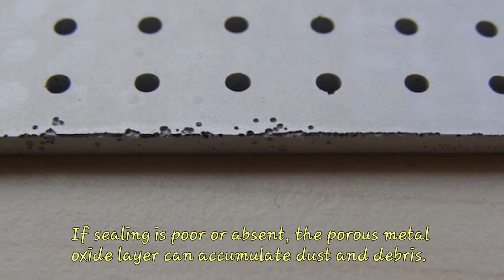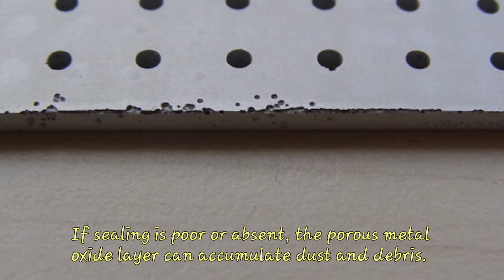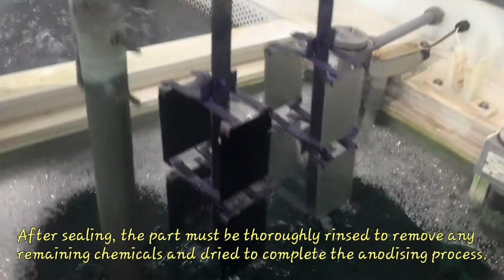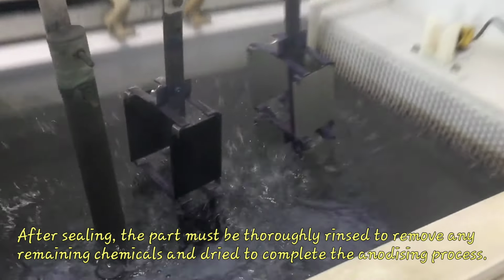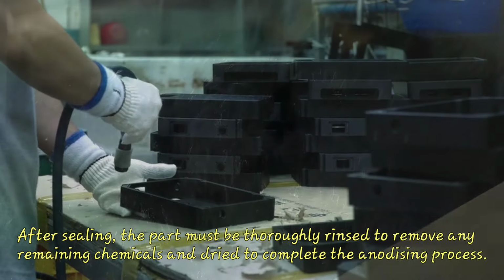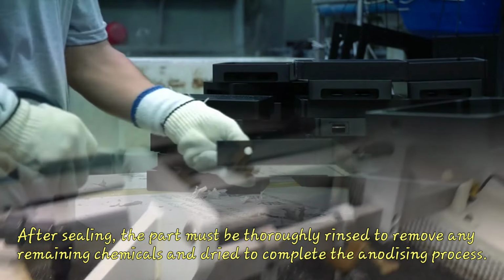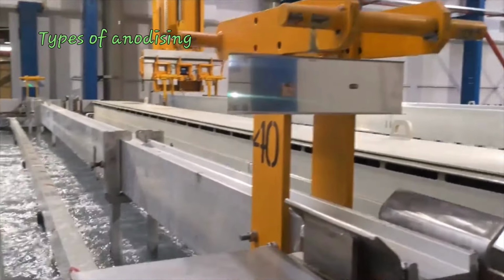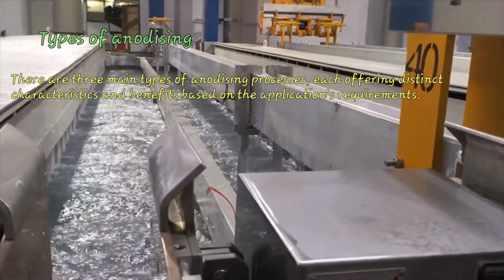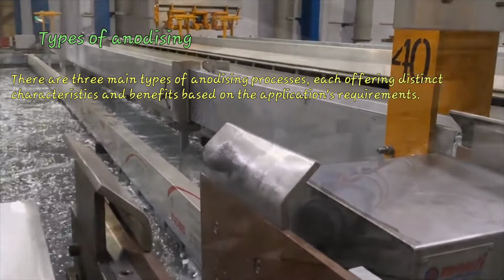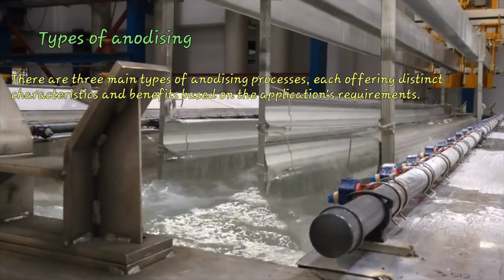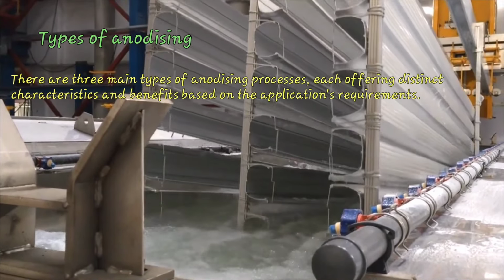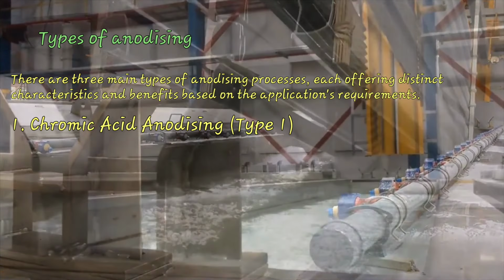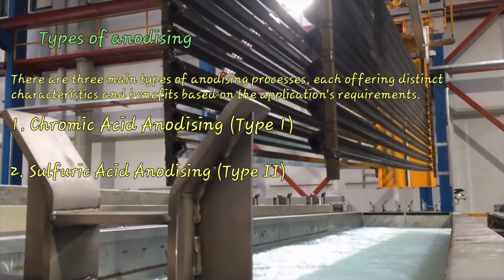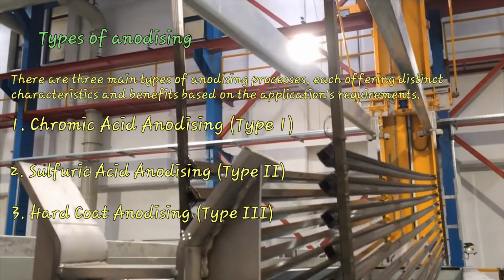If sealing is poor or absent, the porous metal oxide layer can accumulate dust and debris. After sealing, the parts must be thoroughly rinsed to remove any remaining chemicals and dried to complete the anodizing process. Proper rinsing is essential for achieving optimal results. Types of anodizing. There are three main types of anodizing processes, each offering distinct characteristics and benefits based on the application's requirements. They are chromic acid anodizing, sulfuric acid anodizing, hardcoat anodizing.